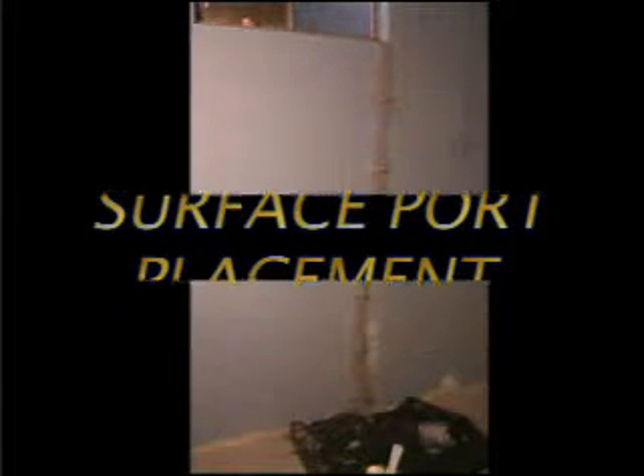Ports are placed apart the thickness of the concrete wall, usually about 8 inches, and centered over the crack. Place the first port starting at point closest to the floor for vertical cracks. If the crack is horizontal, start at the lowest end of the crack. Mark the port locations on the wall as shown.